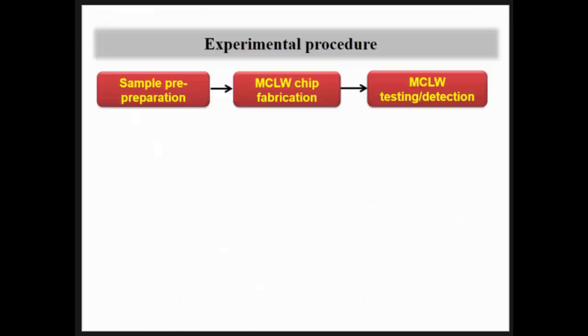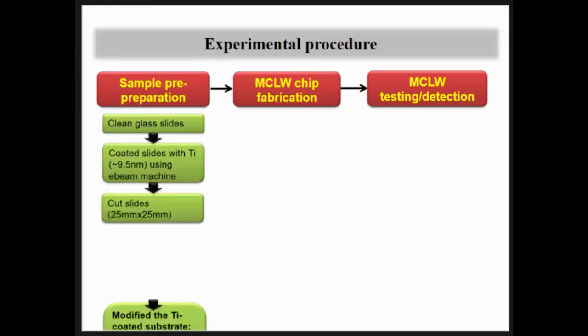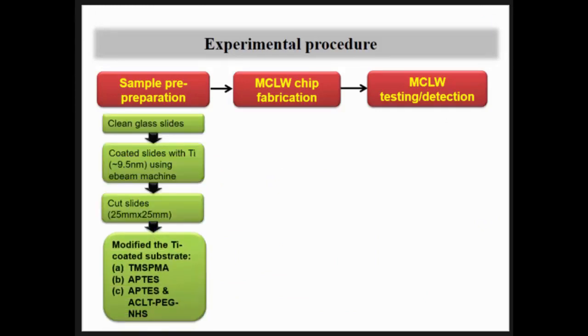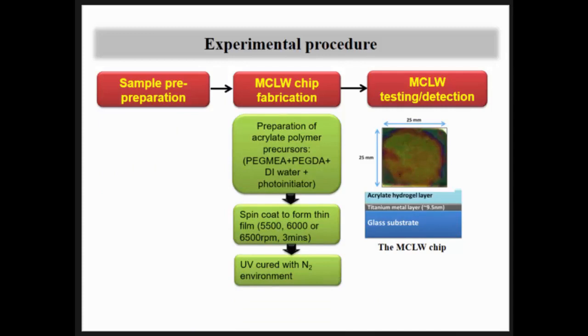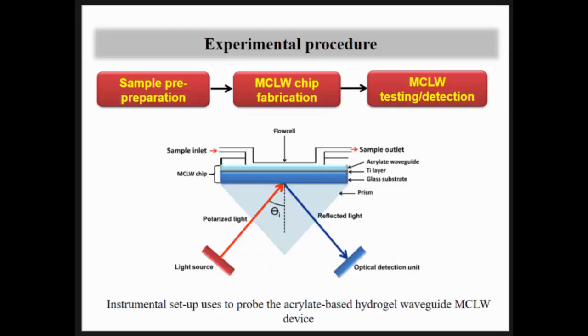So this is the method that I use to prepare my chip and how I do the detection. For the preparation step, this is the common step, but we're adding one step here at the end, whereby we treated the TI-coated substrate with these three sequences. And after that, for the fresh sample, we deposit the hydrogel using the spin coating process, and we cured the gel using the UV lamp. And this is the common probe that we use to get the signal.